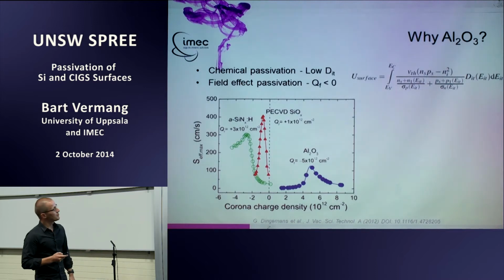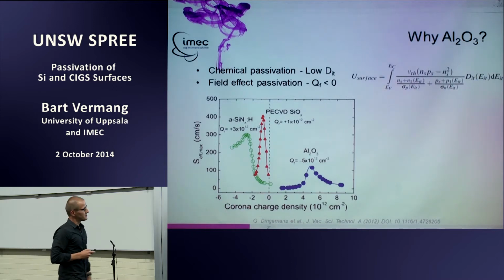So why aluminum oxide? Aluminum oxide for P-type silicon has chemical passivation and field effect passivation. Chemical passivation passivates the interface very well. It's kind of lattice matching, so it will lead to low interface trap density on top of silicon. Field effect passivation: aluminum oxide is one of the only known materials that, if you deposit it on silicon, has a negative charge density, which is also beneficial. For example, you see the formula over there, which is the Shockley-Read-Hall recombination formula. Thanks to the chemical passivation, the Dit will be low. Thanks to the field effect passivation, the minority charge carriers will be low in the case of P-type. There will be electrons, so the ns at the surface will be low.